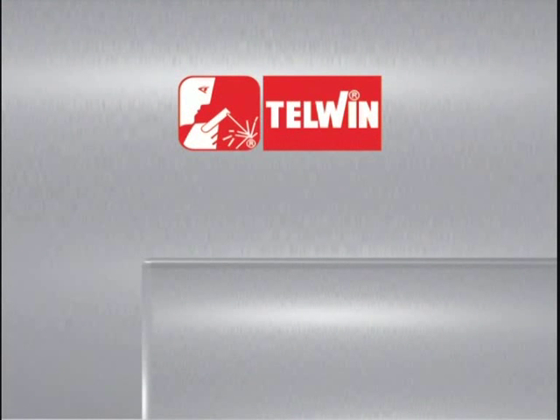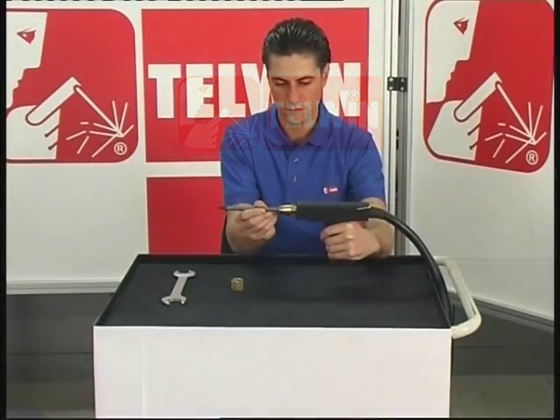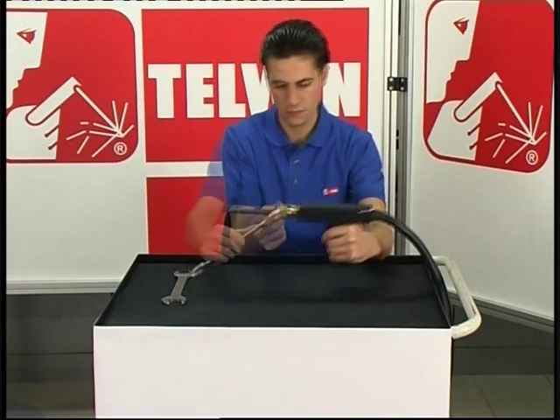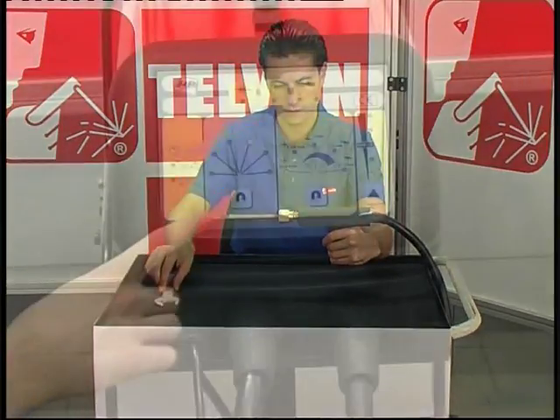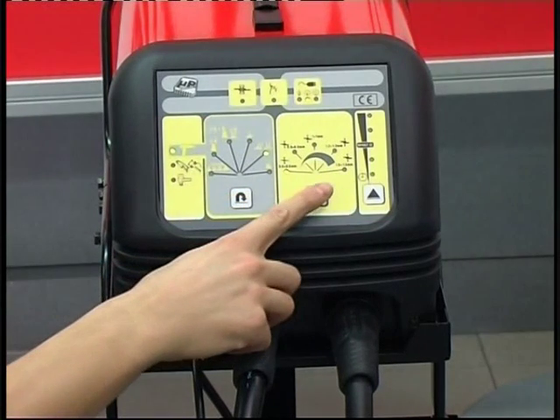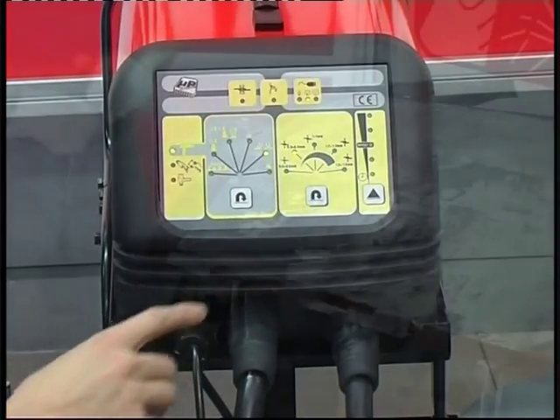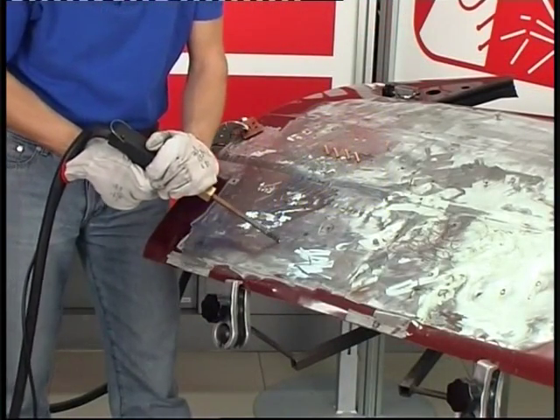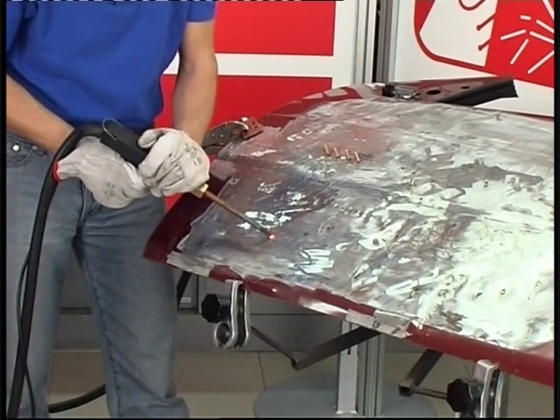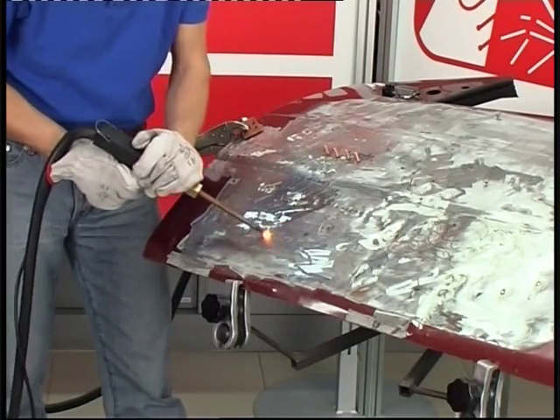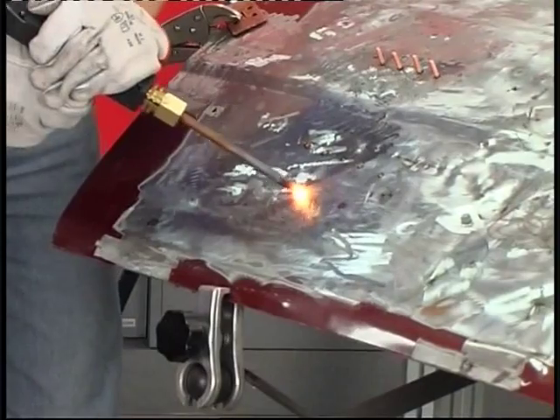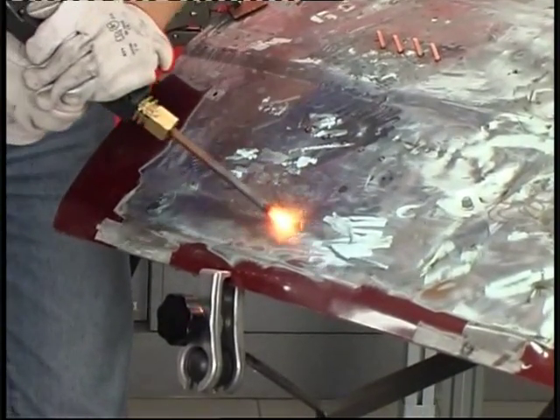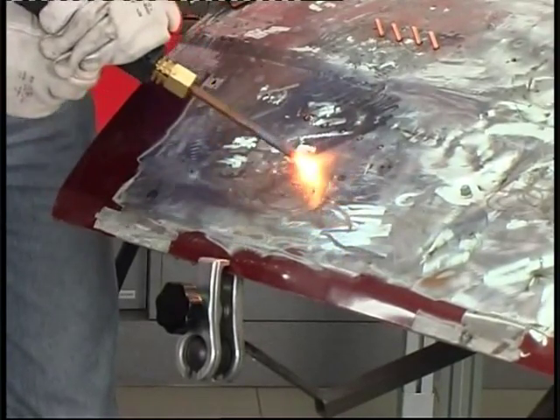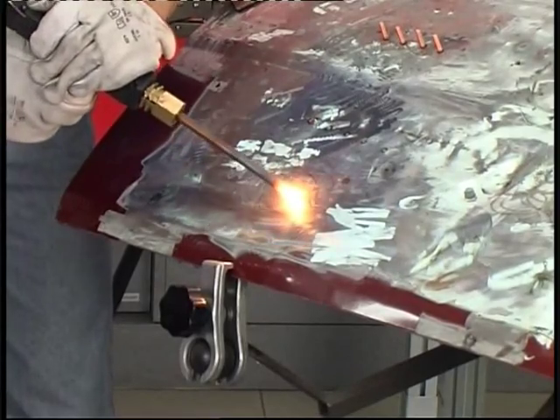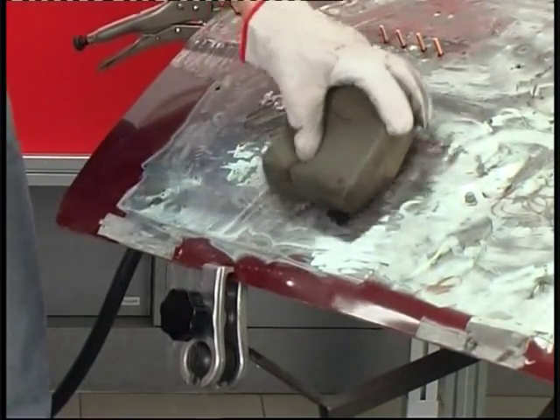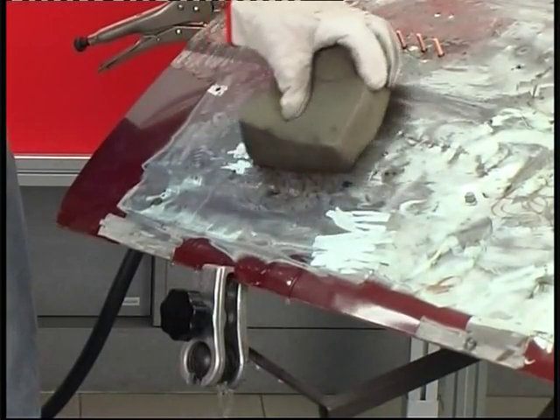Heating and tempering operations. Fit the gun with a carbon electrode. Switch on the machine and set the heating function, the sheet thickness. Work on the operating area from the outside to the inside, moving in a concentric spiral. The operator decides the time taken. Heating the sheet will allow it to return to its original position for shallow dents. To carry out tempering, continue with abrupt cooling using water.